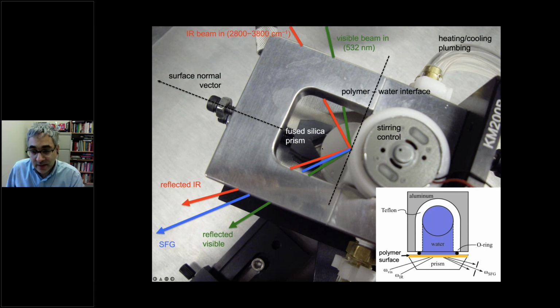And what you see here is a hemicylindrical prism, and this is just a glass prism. But right where I'm showing you the dashed black line is where we coat the silicone rubber. So if we just coat silicone rubber on the prism and we don't do anything else, then we can look at the silicone-air interface to within a nanometer length scale. But underneath this stirring motor I'm showing you is a liquid chamber, and I'm showing you a cutaway of the chamber diagram down below. And we can fill that chamber with water, with salt water solution, and now we can look at the surface of the polymer and the liquid. So we can look at any kind of environmental condition and see what's happening at the top nanometer.